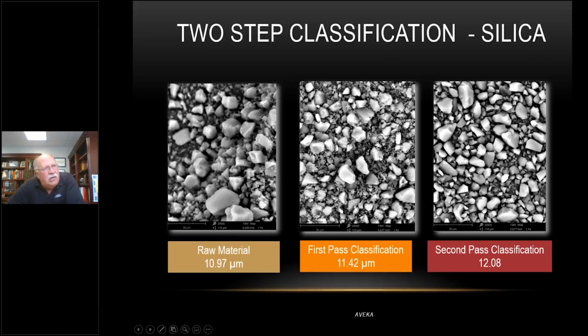We find out that the fines that are inherent in almost every material almost need to be stirred up again and again and again. And when you do flow measurements, dry powder flow measurements, you see the same effect going on. And here we're seeing it in grinding. I'm not sure that I completely understand it. I'm not sure the people that do flow measurements completely understand it, but I can guarantee you that this is one of those big issues in particle processing.